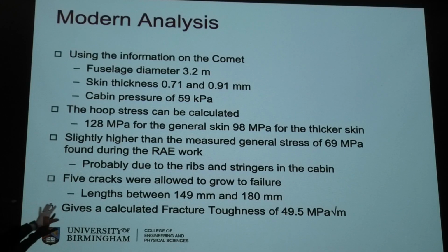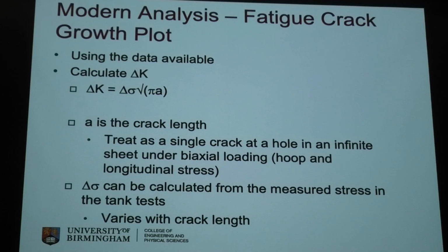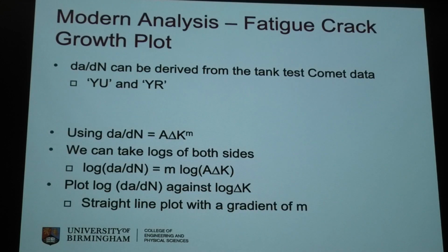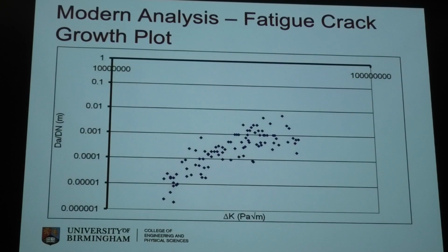Five cracks grew to failure, so we can roughly calculate a fracture toughness of nearly 50 megapascal meters, and we can plug all this together in those equations. And we can calculate the delta K values. I'm going to whistle through this because this is just Paris and Erdogan stuff. You take the data, you plug it into their equation. I'm not going to spend a long time, and somebody can come to me at the end and we can go through the maths if you want.